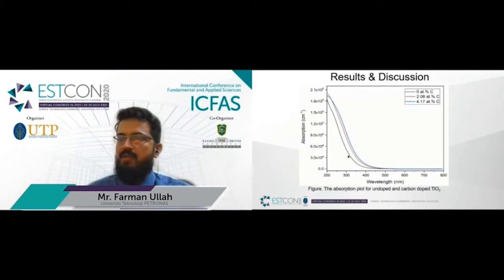For the pure TiO2 model, the optical absorption edge is around 380 nanometer, which is extended to 450 nanometer for the carbon doped TiO2 sample due to the reduction of the band gap energy from 3.13 electron volt to 2.52 electron volt.